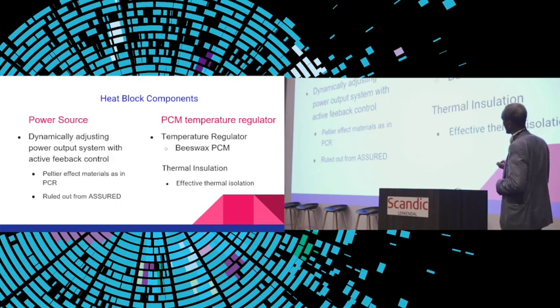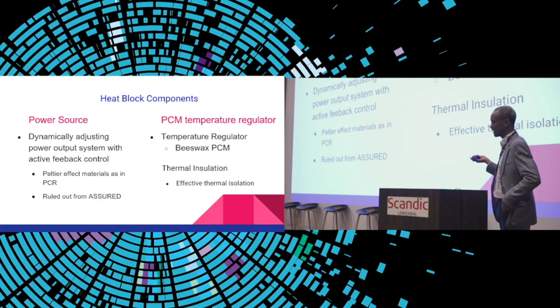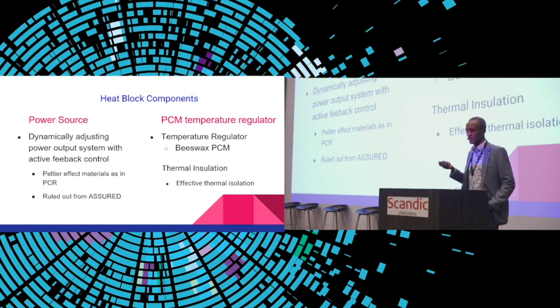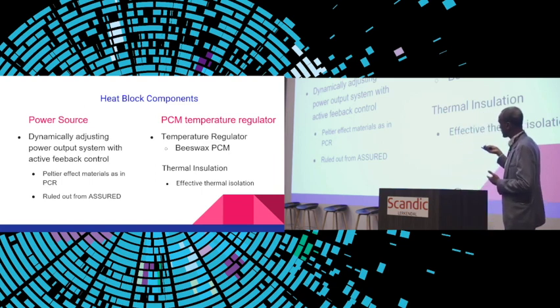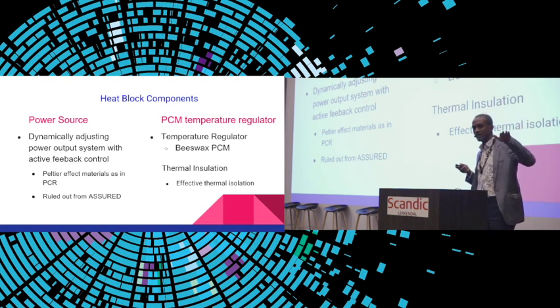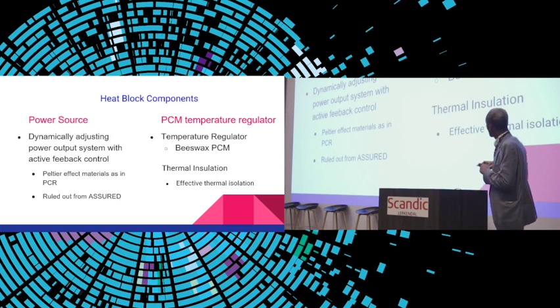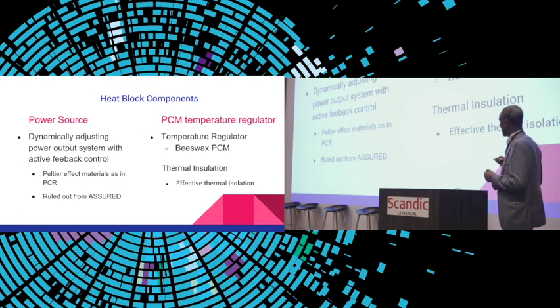Had it been in a developed country where electricity is available, we could use a Peltier effect material, as in PCR, but that one is equipment intensive. So that is ruled out by applying the ASSURED criteria. We opted for a phase change material. As you know, when materials change their phase, they maintain a constant temperature, which is the latent heat of fusion. For that, we selected beeswax. Coincidentally, beeswax melts at the temperature that is the amplification temperature for most bacterial and viral samples. So with effective thermal insulation, we hope that we can realize it.